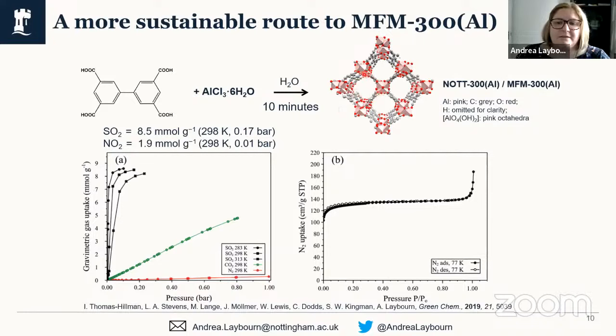Because this material has not been prepared porous to nitrogen other than by our hands, we do not yet have a proven reason why this material uptakes nitrogen. What we think might be happening, and our current working hypothesis, is that we are producing an MFM 300 framework that is defective, and so this is allowing the nitrogen to penetrate into the structure, which you don't see with the conventionally heated material. But we do have ongoing investigations in the group to further uncover information about this.